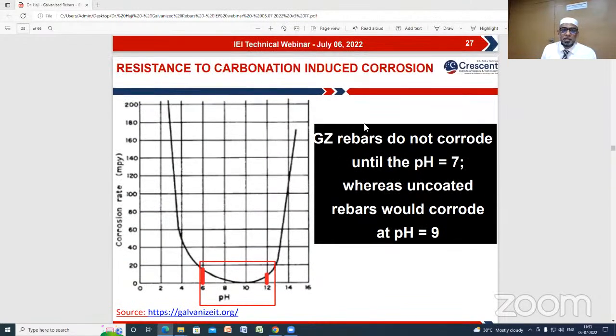Another important advantage when you go for a galvanized rebar is, as I told earlier, that the pH of the concrete is 12 to 13, and due to carbon dioxide penetration, there will be a reduction in pH in the concrete. Once the pH of the concrete comes to 9, the concrete will not give protection to the steel, and the steel will start corroding. This will happen in the uncoated conventional rebar. But scientifically, it is proven that in the galvanized rebar, until a pH of 6, it won't allow the steel rebar to corrode.